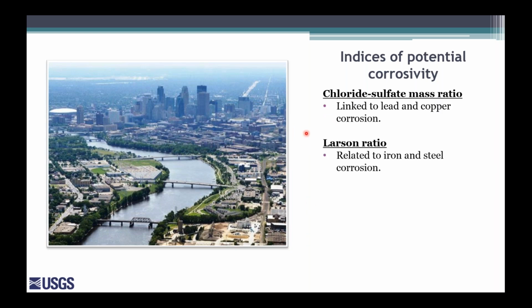The chloride to sulfate mass ratio has been linked to lead and copper corrosion, and this has been shown in water distribution systems as well as in benchtop experiments, and it acts by promoting galvanic corrosion. Galvanic corrosion occurs when two dissimilar metals come into contact with each other, and this is most important in systems that have had partial lead service line replacement, as I mentioned a bit earlier. In some cases you'll have the city replacing its portion of the water distribution system, and there is a point where there's a junction between the replaced pipe and the old lead pipe, and that junction can be a place where this galvanic corrosion can occur, and this is promoted by high chloride to sulfate mass ratios.